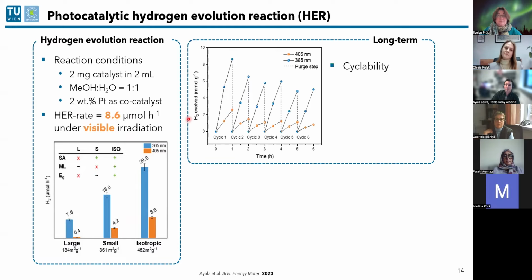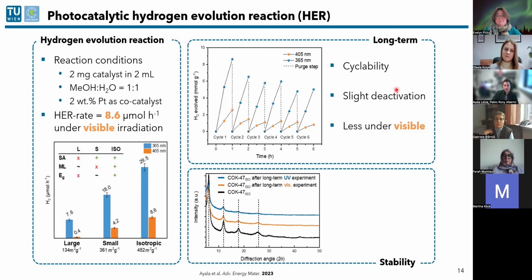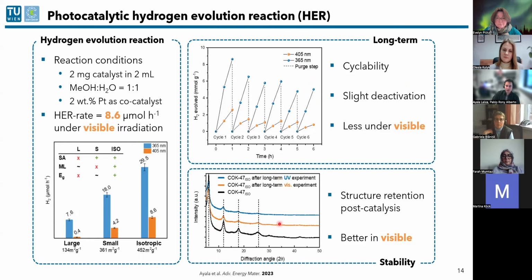So then, of course, we're also interested in cycling this material. So we did also some cyclability experiments where we illuminate and then purge and subsequently so. And we saw a slight deactivation, especially under UV light illumination. But we saw that this deactivation was a bit less under visible light illumination. So that is also good and speaks for using this material for visible light applications. And also, of course, stability is very important for MOFs. We saw structural retention, and this one was also better if we did not use UV light, but rather visible light.